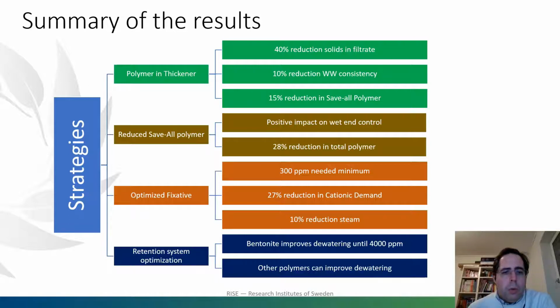And also, when we worked with the retention system, we saw that even if the bentonite was limited, in the sense that over a given level we were not able to improve the dewatering further, by the addition of other polymers we could even improve the dewatering better.